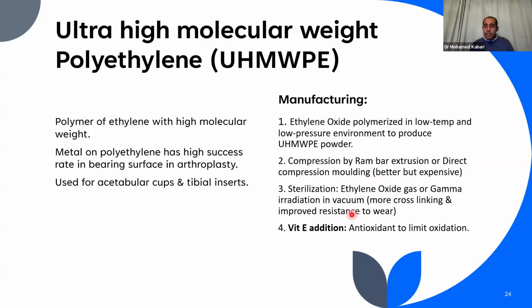Then it passes through the sterilization of the polyethylene. It's sterilized by ethylene oxide gas or gamma irradiation in a vacuum, to avoid oxidation in the air, so it should be done in a vacuum area. And this will lead to more cross-linking and improve the resistance to wear. And the last thing is addition of vitamin E, which is an antioxidant to limit the oxidation of the polyethylene.